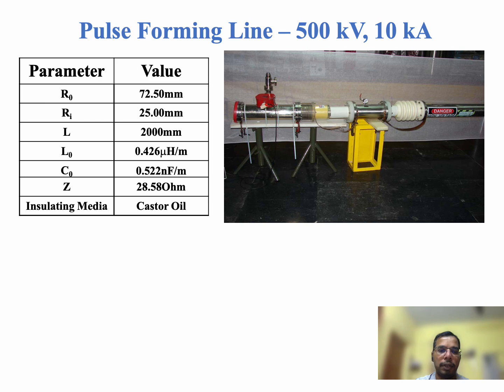The parameters that we have designed are an outer radius of 72.50 mm and an inner radius of 25 mm, with a length of 200 centimeters. The inductance and capacitance values and the characteristic impedance of 28 ohms are shown here, and the insulating material used is castor oil.